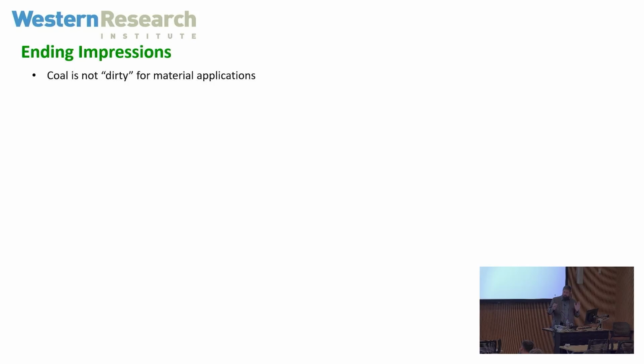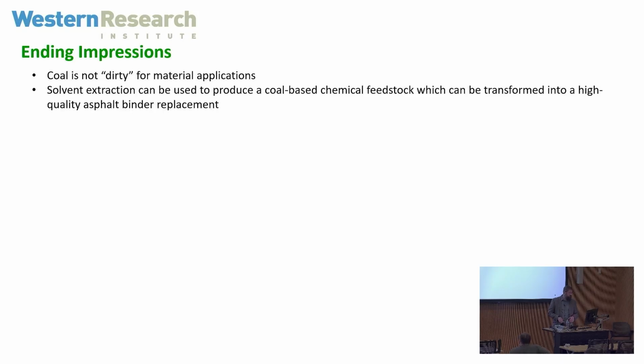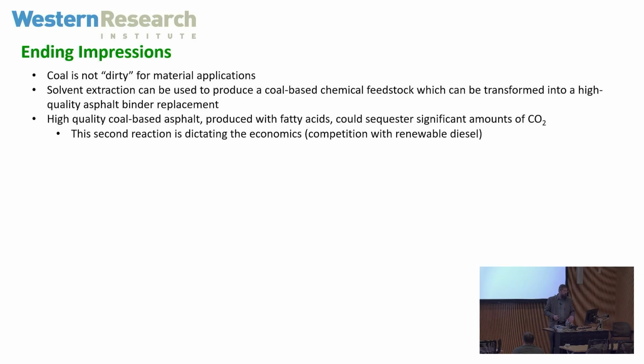So in the end, is coal really this dirty thing that we should just leave in the ground and forget about it? Well, if you look at it from a material application standpoint, and again, I'm not showing all the energy inputs to make the final product, but as a raw feedstock, it actually makes a lot of sense. It has a very low carbon footprint. Solvent extraction, we found, is a really good way to utilize a huge amount of the coal to transform into high quality asphalt binders. And if we use fatty acids, we can add additional benefits, which is to sequester CO2.